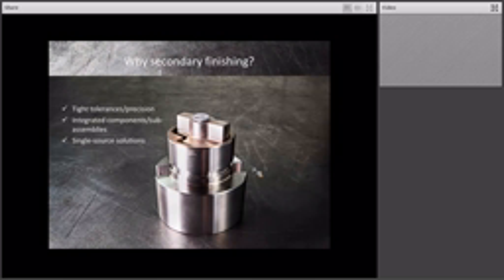So why secondary finishing? Why would you do it? Well, the tolerances may become too tight for the powder metal net shape component to hold. Again, it depends on the diameter of the component, but if you've got a 3-inch, 4-inch outer diameter component, you can't hold much more than perhaps 8/1000ths of an inch in tolerance. And if you need to get tighter than that, then you may have to add secondary machining. In the case of the component you see before you, I believe it has 8/10,000ths of an inch of tolerance on the diameter. And that part is rough turned, fine turned, and then ground precisely on lengths and diameters.